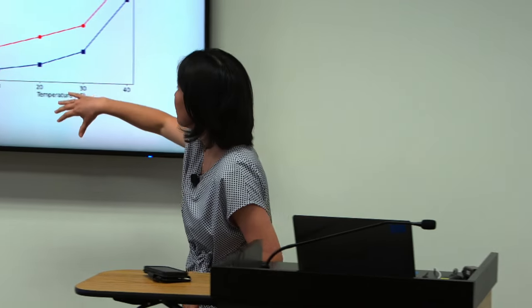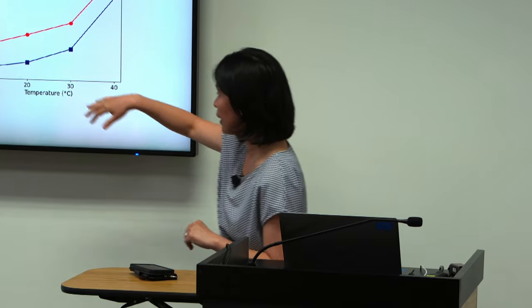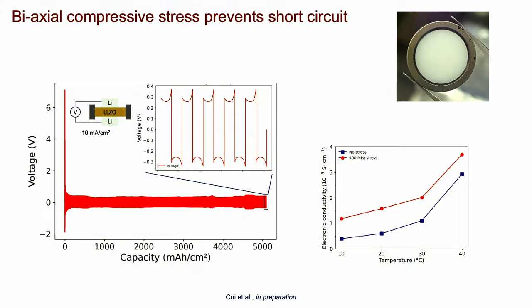Okay, looking at what else is changing in the material. We have the transport of electrons or ions across the solid electrolyte. At least for the electronic conductivity under this amount of applied stress, there is a slight elevation of electronic conductivity, but that would actually give more reason to believe that we would form small lithium pieces that would form dendrites across our material. So it is actually further strengthening our idea that the mechanical stress is really controlling everything that's going on here.